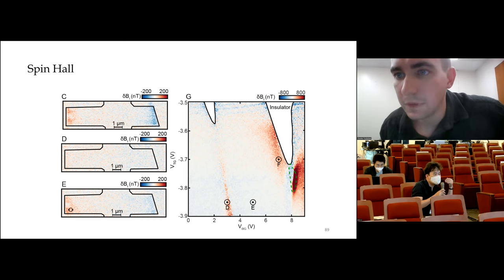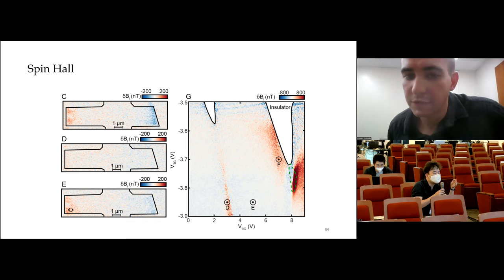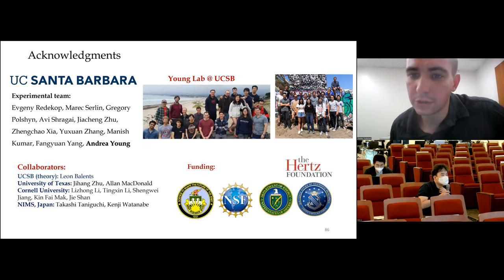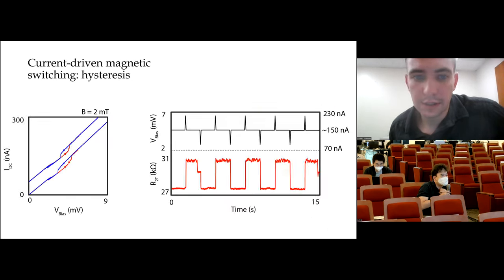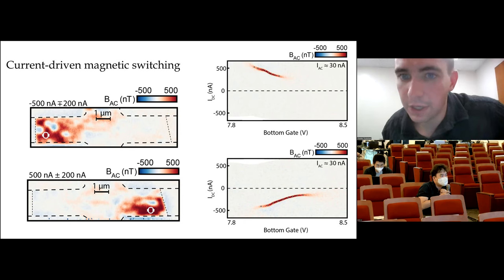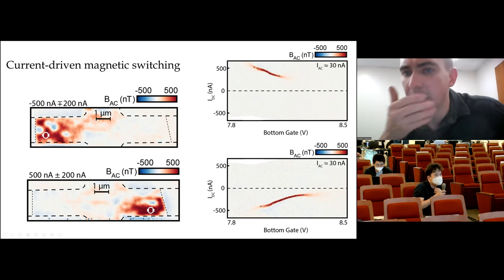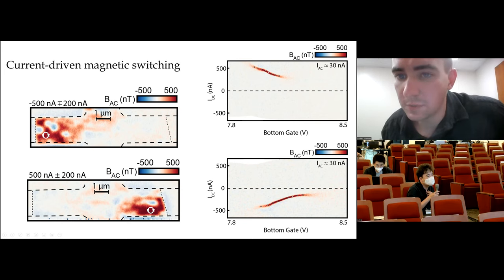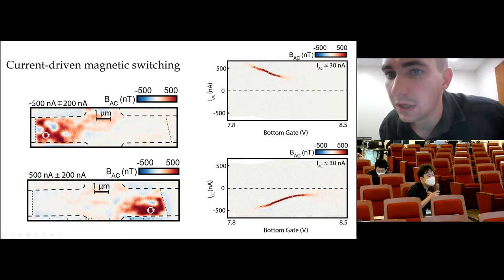So the mechanism is correct. Is there a threshold for this to happen? Like when you increase the electric field, initially it doesn't happen, but... Yeah, exactly. I was calling that the critical current, as these plots on the right show you as a function of DC current, where we see this local spin flipping, magnetization flipping phenomenon. In most regimes, it doesn't happen at zero bias current. It's a situation where you have a finite critical current or critical bias, and then it happens when there's enough spin accumulation.